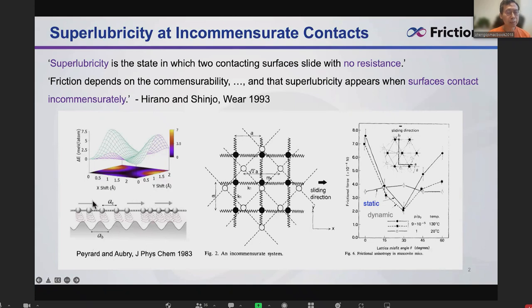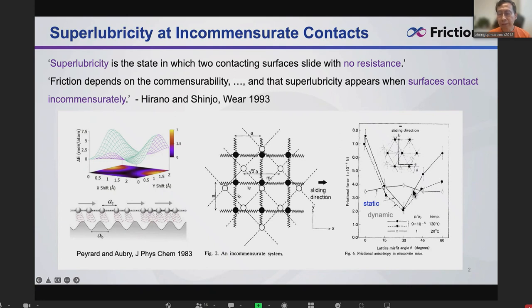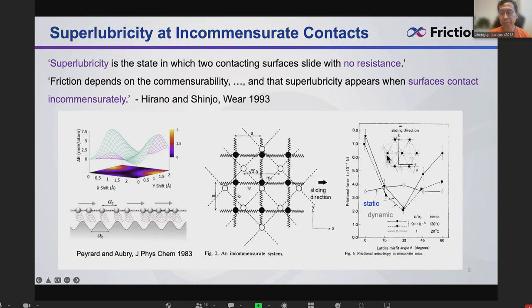From the literature, a mathematical model showed that when surfaces are somehow incommensurate in one dimension, that will result in canceling the shear resistance. This experiment was done by Hirano and colleagues. You can see the difference between static and dynamic friction — dynamics is slightly lower than statics, but very similar — with dependence on the mismatch angle between two graphene or graphite layers.